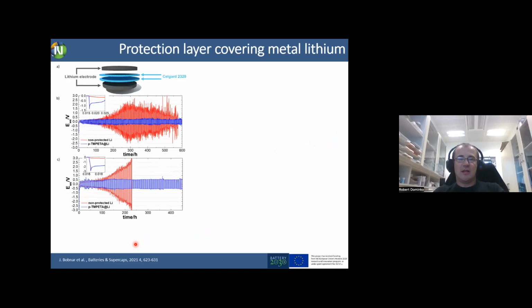So we started to work on that, and the first attempt was with a student on fluorinated graphene and graphene oxide, but then we moved to one polymer which should be a very good ionic conductor for lithium. This is so-called TMPTA, and we observed, okay, it works better if we have this layer on top of the lithium metal, compared to the non-protected lithium. And moving from 0.5 milliamp hour per square centimeter to 1 milliamp hour per square centimeter, we can see even better. We see some polarization in the first cycle, which means that there should be a formation of ionically conductive pathways, and that's it. Stopping here, we would be happy, and we can publish this.